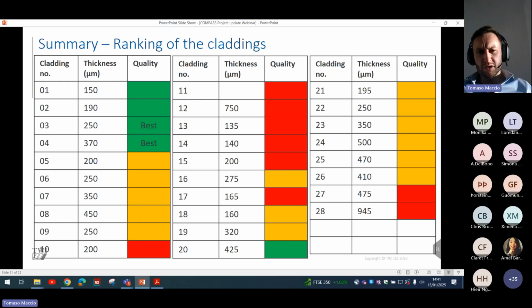So from the samples, we've then ranked all of those samples, giving a layer thickness and also a score on porosity. The porosity measurements aren't in this slide deck, but we've done a porosity measurement as well, and we've thresholded that and mapped that out as well along with this to choose the best parameter set that we'll go forward with for testing.